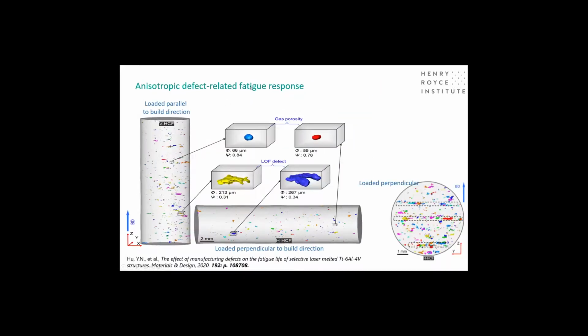We can also understand the effect of those anisotropic defects, those lack of fusion defects that I was talking about earlier. So you can see that the gas porosity is generally spherical, but these lack of fusion defects tend to be more pancake shaped. And when we look, this is a sample which was on the left. You can see a sample where the build direction is along the tensile axis of the fatigue sample, whereas on the right we can see a sample which is loaded perpendicular to the build direction.